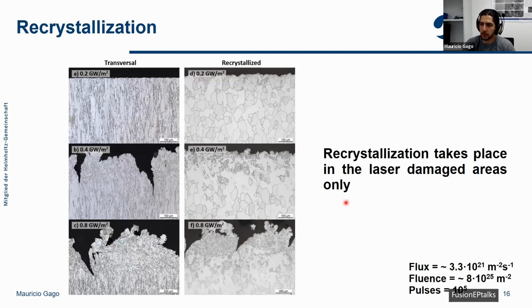And then another process that is taking place during the tests is that of recrystallization. As I mentioned before, it is expected in the PFMs, and we can see that during these tests as well, on the areas affected by laser, recrystallization is taking place, and this does not happen in the areas affected only by plasma, for example.